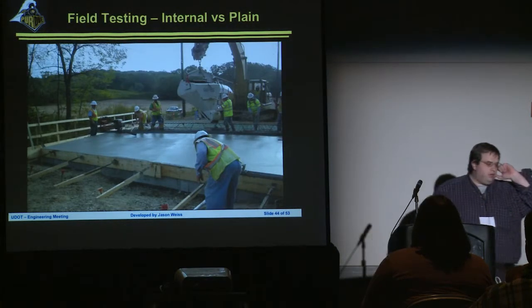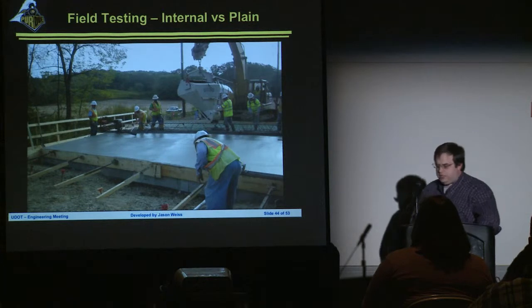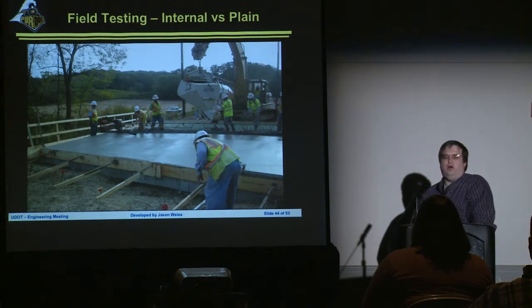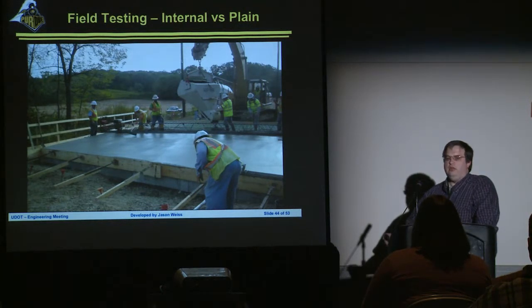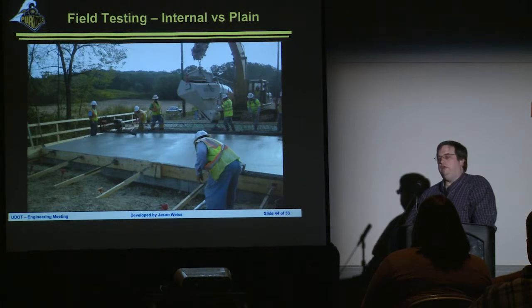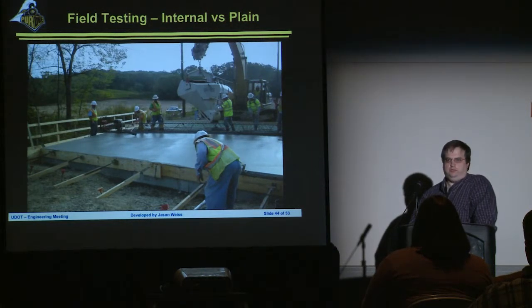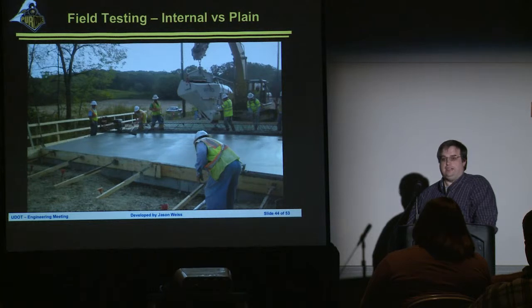Now, some of the things that I will mention here, this is some field testing that's been done. There are about 12 bridge decks that have been done in New York State. We've walked these, with the exception of one deck that I think has some structural vibration issues. They all have, at most, one crack that we saw in the negative moment region. And it's a very small crack because there were 16 of us standing out there, with one guy on his hands and knees looking for this crack.